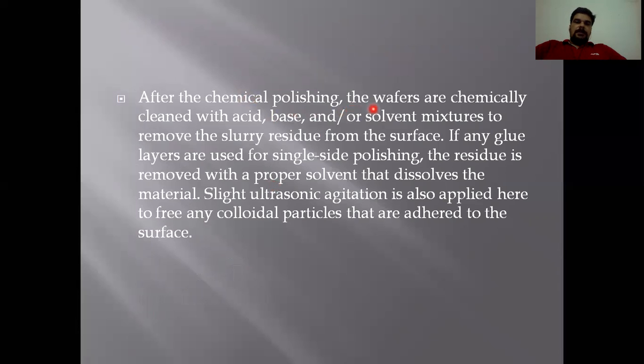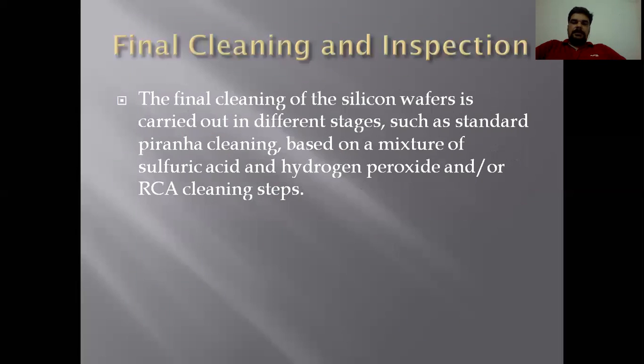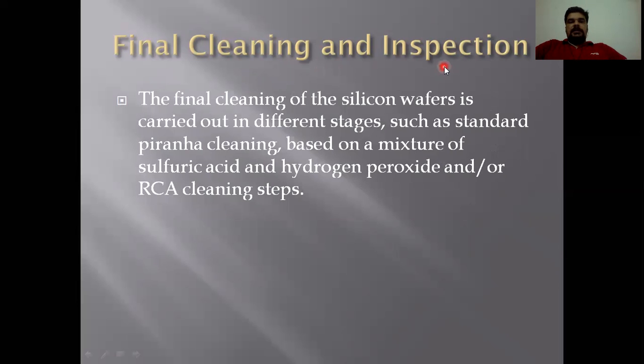Now after chemical polishing, wafers are chemically cleaned with acid-base or solvent mixtures to remove residue. If any glue layers are used for single side polishing, the residue is removed with a proper solvent, dissolving the glue. Now there is the final cleaning and inspection process. Final cleaning of the silicon wafer is carried out in different stages, such as the standard RCA cleaning based on a mixture of sulfuric acid and hydrogen peroxide, and other RCA cleaning steps. So this was the final cleaning step before the packaging of your silicon wafer.